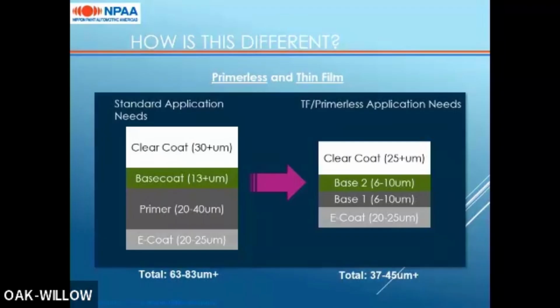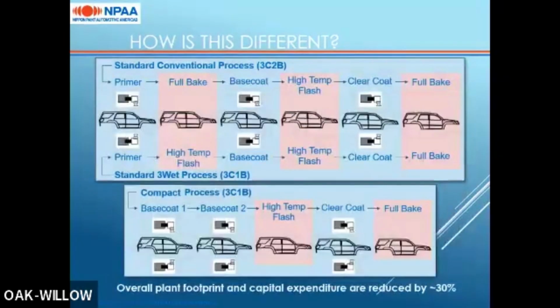And it shrinks that down, turning the primer into a base coat with some primer functionality of 6 to 10 microns for most colors, a second base coat also of 6 to 10 microns, and the clear coat is reduced by about 5 microns for 25 microns total. So this gives a total top coat film build of 37 to 45 microns for most colors. There is some variation for colors that traditionally have poor hiding, such as whites, where film builds are higher. So the additional benefit there comes in from the compact line design for this coating.